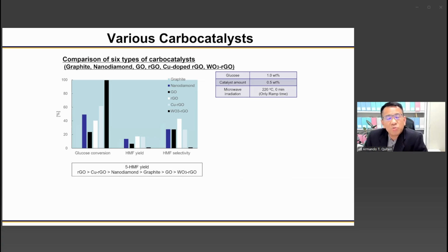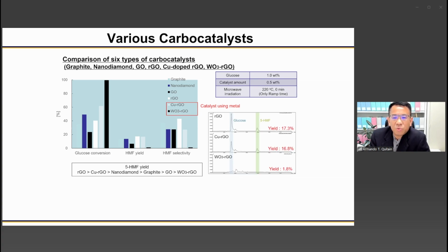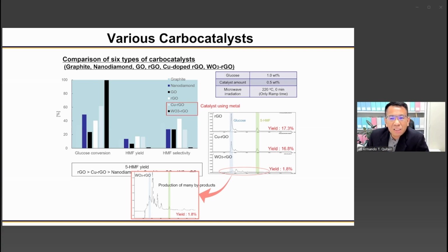We tried various carbocatalysts other than graphene oxide. We also use reduced graphene oxide. We even compare it with nanodiamond and graphite. We even dope reduced graphene oxide with metals such as copper and tungsten in combination with the reduced graphene oxide. And we check the ability of these various types of catalysts on the production of 5-HMF from glucose. And we found out that among these catalysts, still reduced graphene oxide performs the best.